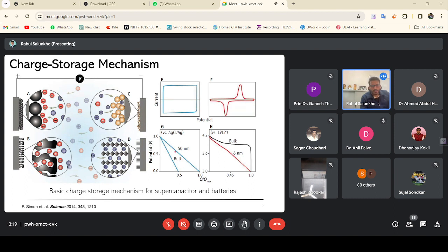We have seen that if our sample is of 50 nanometer thickness or it is a bulk, depending upon the sample thickness, the discharge profile can be observed. For small thickness, more charge can be stored because more surface area is accessible to the electrolyte ions. Whereas in the case of a bulk, there is a certain dead weight that is not accessible to the electrolyte, and because of that less charge can be stored.